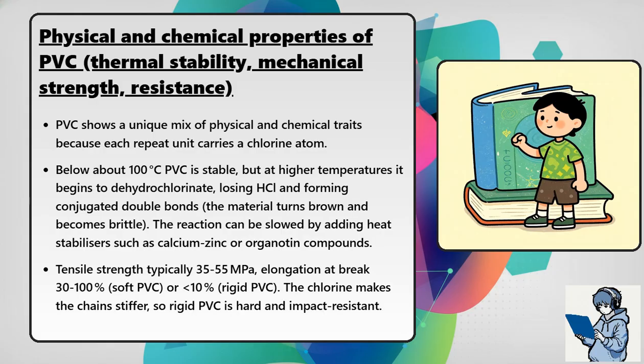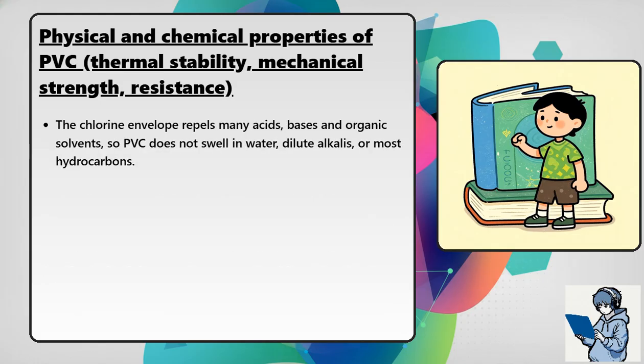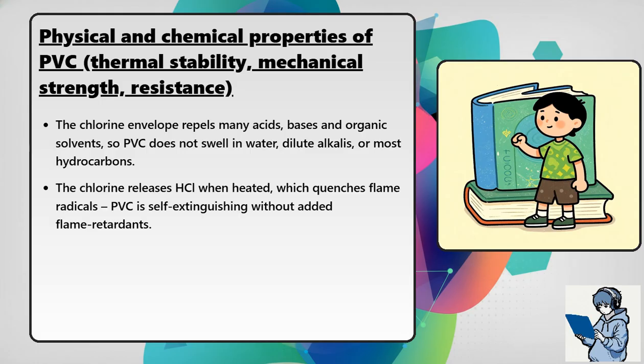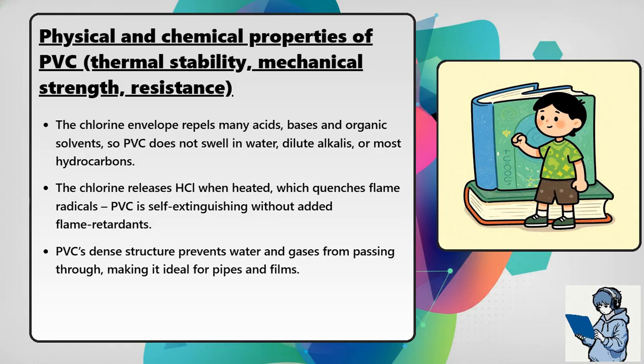Tensile strength, typically 35 to 55 megapascals. Elongation at break, 30 to 100% for soft PVC or less than 10% for rigid PVC. The chlorine makes the chains stiffer, so rigid PVC is hard and impact resistant. The chlorine envelope repels many acids, bases, and organic solvents, so PVC does not swell in water, dilute alkalis, or most hydrocarbons. The chlorine releases HCl when heated, which quenches flame radicals. PVC is self-extinguishing without added flame retardants. PVC's dense structure prevents water and gases from passing through, making it ideal for pipes and films.